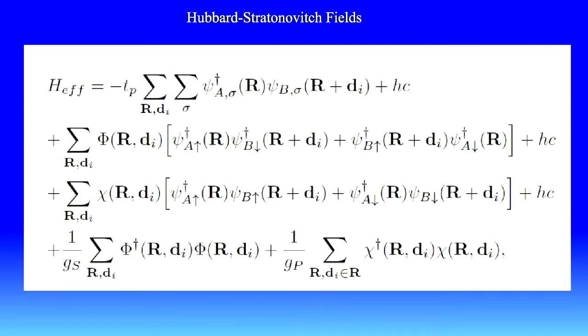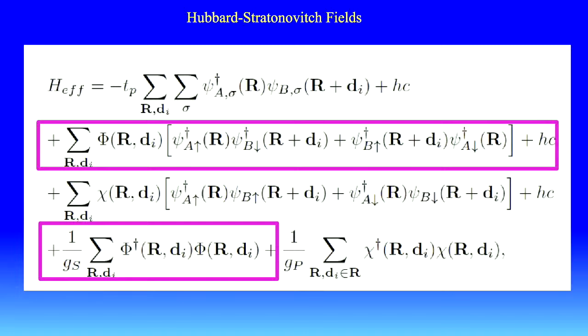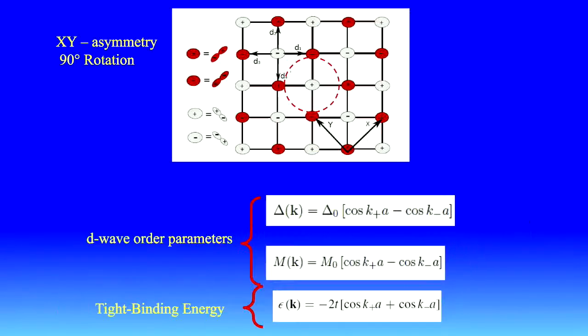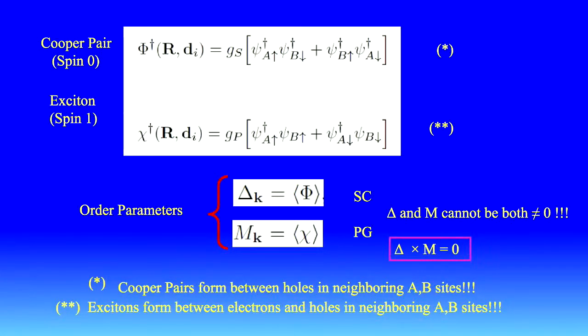So here we use the Hubbard-Stratonovich method to write this as a trilinear term, where phi is a Hubbard-Stratonovich field. So I do this for both and obtain the equation for the phi and chi fields. So the expectation value is the expectation value of a Cooper pair. So this is an order parameter for superconductivity. And this M, which is the expectation value, is going to be an order parameter for the pseudogap. I'll show that. And we can show very clearly that both cannot be different from zero at the same time. So there is a competition between pseudogap and superconductivity.